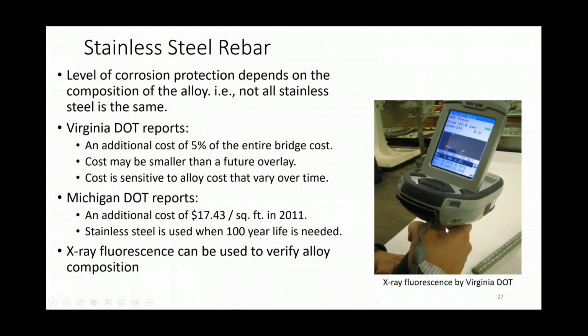So one interesting thing that we learned from Virginia DOT is on the right-hand side. They do have these X-ray fluorescence handheld devices, and it can actually tell you the composition of that alloy. So they were using it to verify essentially that what you specified was the same as what they received from the manufacturer. So that, I think, is the quick way to check the alloy, and of course, specifying the type of the stainless steel in the specifications is important.